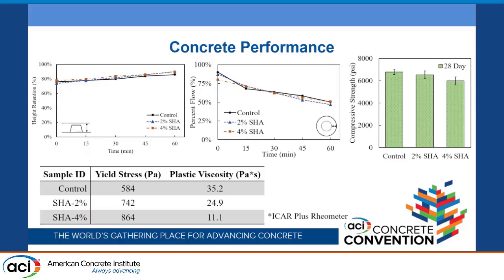We then also did testing with the ICAR plus rheometer, just to gather some information on our yield stress and plastic viscosity. Our yield stress is on the lower end of what you'll see in literature, but it is still in the range acceptable for 3D printing from what we saw.